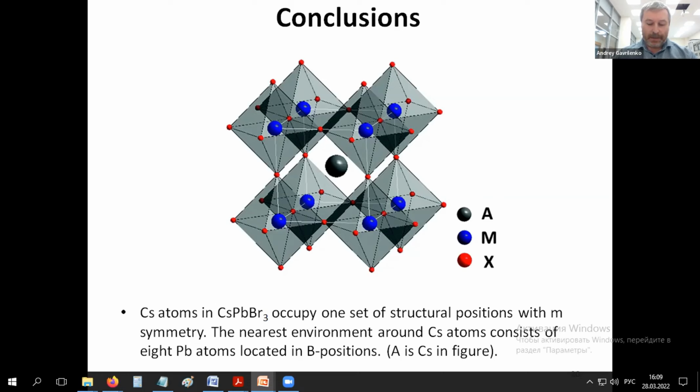For the cesium NMR spectra of the doped CsPbBr3 plus bismuth samples, a set of satellite lines is also present. However, the peaks of the resonance lines for the central transition in the doped samples are slightly shifted down and occupy the region between 117 and 115 ppm. It can be noted that narrow resonance lines in the spectrum are retained in doped samples as well.